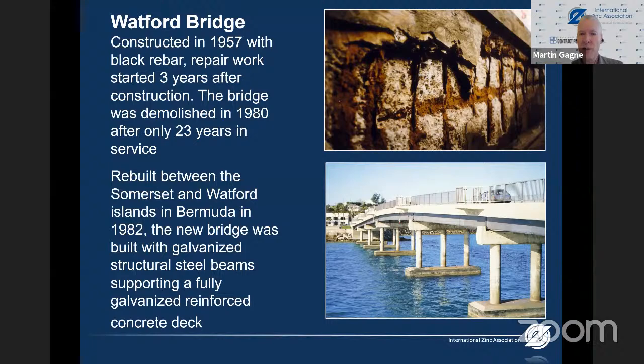Galvanized reinforcing steel was used in the concrete piers and the bridge deck, but also hot dip galvanized steel beams were used to support the bridge deck. So now this bridge is almost 40 years old and it's still in excellent condition. There's no staining, there's no cracking, spalling, and there's no corrosion of the hot dip galvanized steel beams either. So using zinc coatings, whether in the concrete or out, is an excellent choice for corrosion protection.